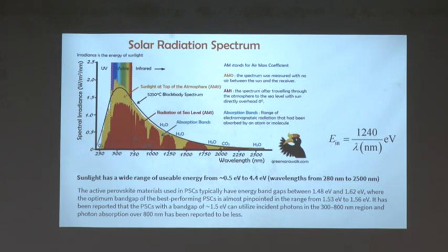And from such a point of view, we have the opportunity to improve spectral absorption, because the energy of the sun is, almost on the ground, from 300 nanometers up to 2.5 micrometers, and it is a great problem because we should adapt our solar cell absorber to absorb most of such radiation to use it properly.